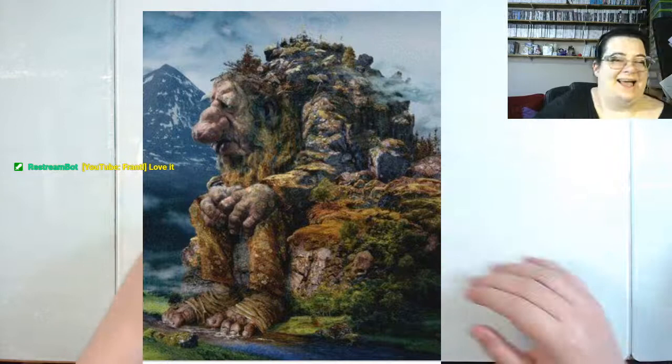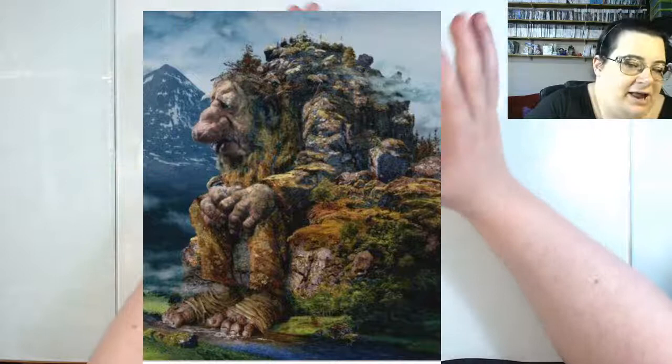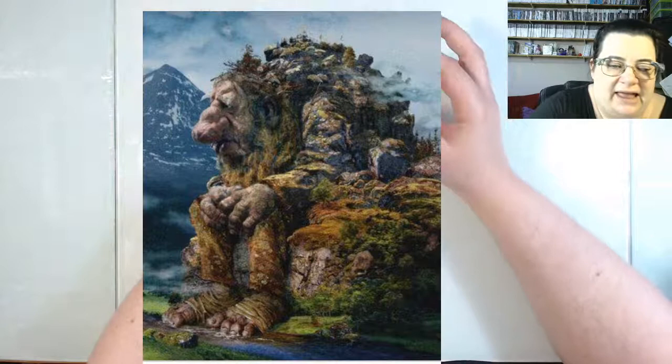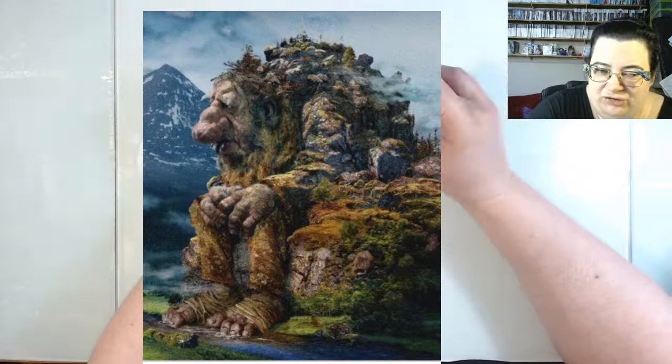So I thought this is a way I can really explore working on rocks but make it interesting for myself. When I started thinking about how to go about making it, that would be a massive slab of clay. If I made the whole thing solidly from clay, it would be really hard to get that center up to temperature without burning the outside. And if your polymer clay doesn't hit the temperature on the packet, so for Fimo it's 110, it stays soft, so you end up with this hard shell soft center, which is really unstable, so you're prone to cracks.